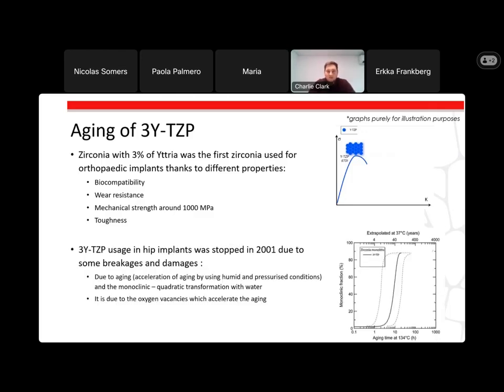However, there is a problem with using the zirconia in hip implants, for instance. This was stopped back in 2001 due to some breakages and damages. What would happen was that the zirconia would age, which was accelerated by the humid and pressurized conditions inside the body. And so the structure of the material would change to a monoclinic structure. And monoclinic would mean that the part itself would lose some of its mechanical strength.